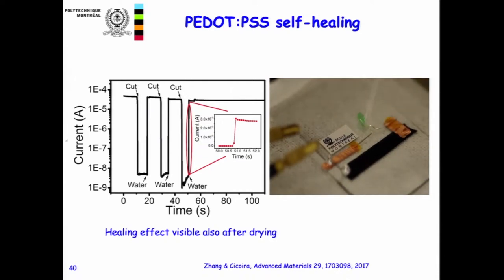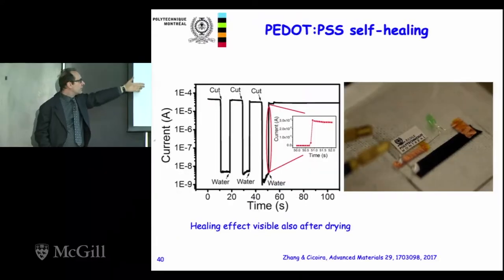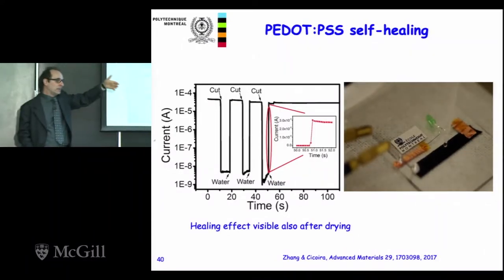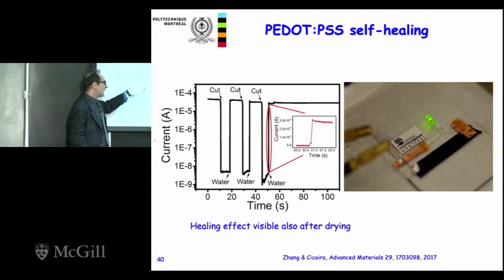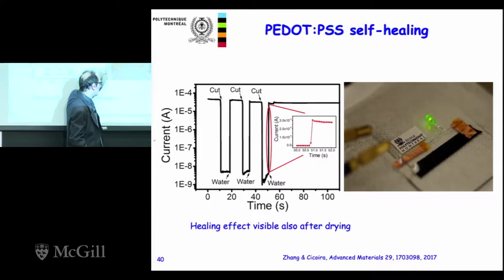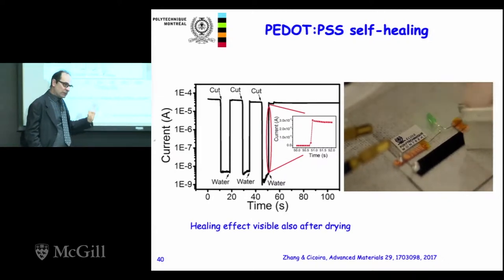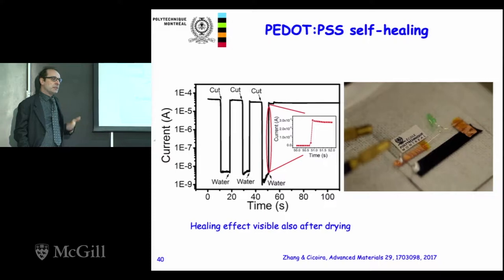But then we put some water, and the current is back. And you see here that current is really back. So this is the current before the cut, and this is after you put the water. So it's really a water-induced healing. And the nice thing is that it's kind of reversible. It can happen many times. We can cut the film as many times as we want on different locations, and we can still heal it.